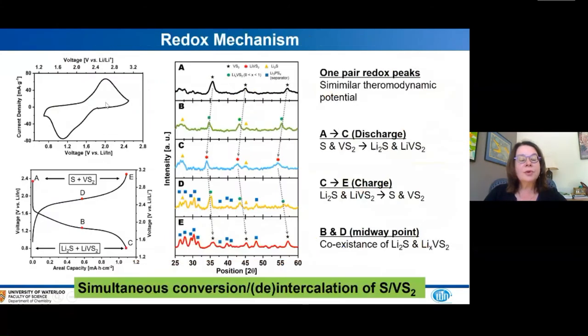The first thing we noticed was that the CV shows only two redox peaks, cathodic and anodic, suggesting that the redox potentials we're seeing in the system are at least overlapped. We don't see separate potentials for the sulfur to Li2S redox compared to the intercalation of lithium in VS2, so we have very smooth features in the solid state battery itself. You can see really just a smooth discharge and charge profile for this combination.